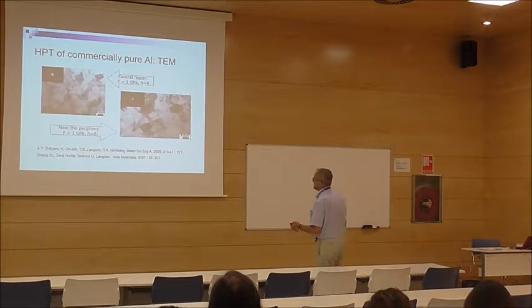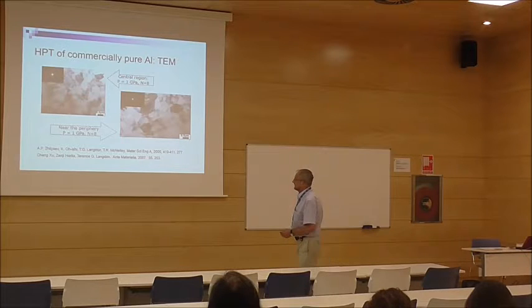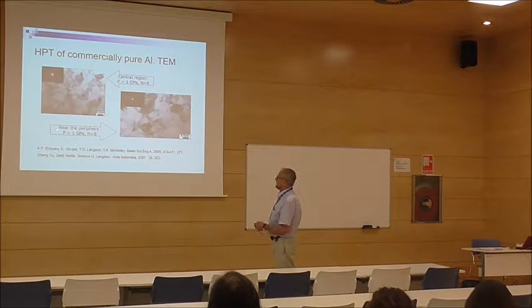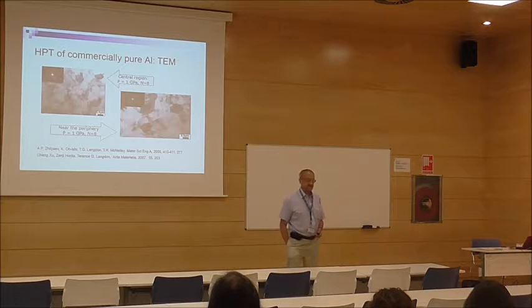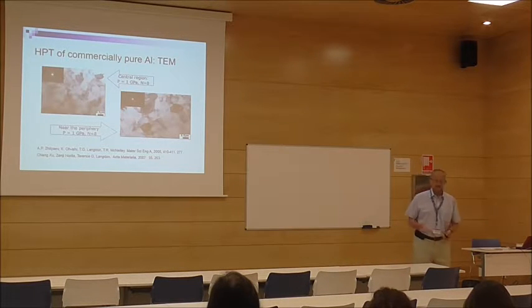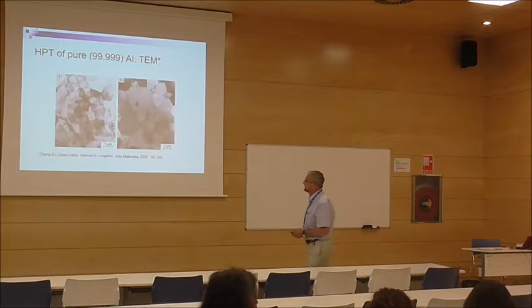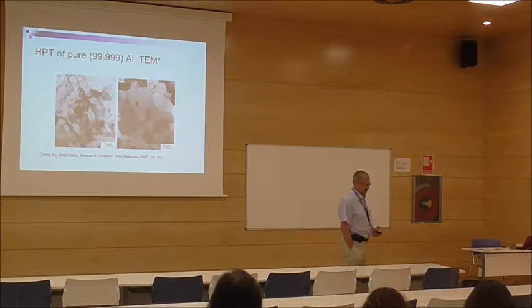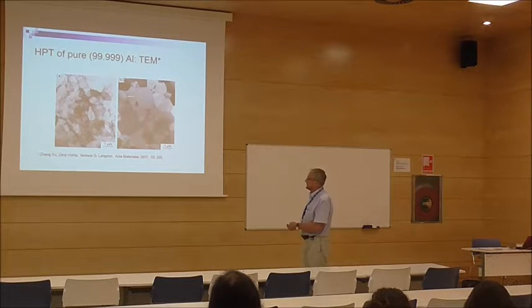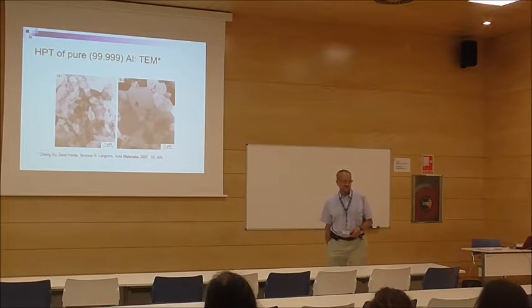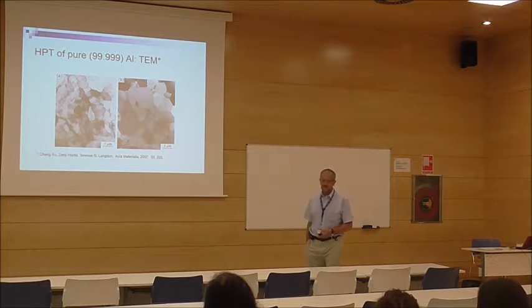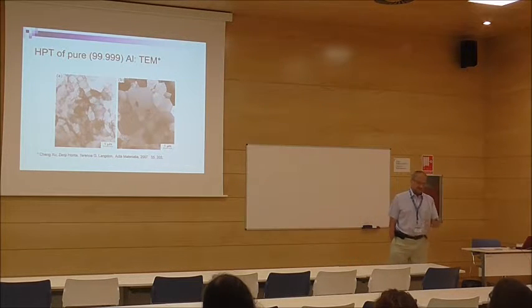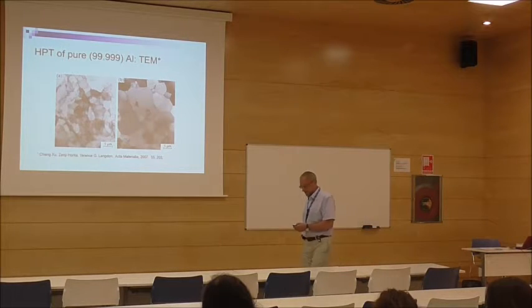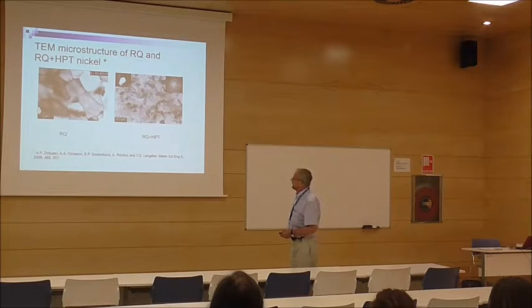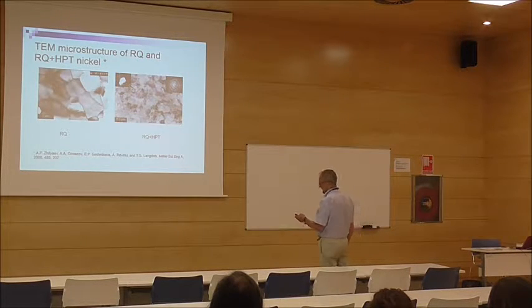At the same time, in commercially pure aluminum, we discovered with Terry that sometimes the grain size near the edge is bigger than in the center. It's controversial, because strain at the edge is much higher than in the center. And Terry was smart enough to repeat this experimental work for high purity aluminum, and found that actually recrystallization takes place during room temperature high pressure torsion of the aluminum. So depending on the purity of materials, you can get either strain hardening, or just recovery, or even recrystallization.